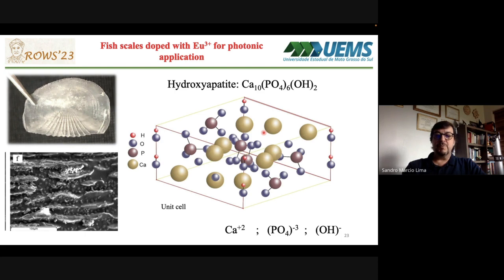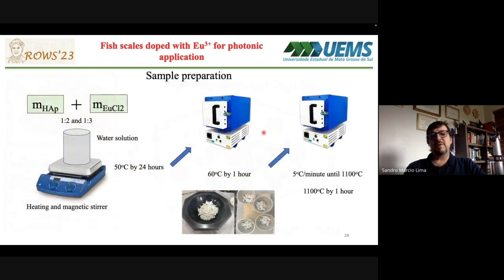So, after removal from the fish, the scales are washed with distilled water to remove the dirt, and following that, they were dried to be weighed and mixed with a mass of europium chloride in different proportions. We tested one per two and one per three. Both masses were mixed in a water solution at 50 Celsius degrees for 24 hours. And after this procedure, the dried samples were heated in an oven at 60 Celsius degrees for 1 hour.